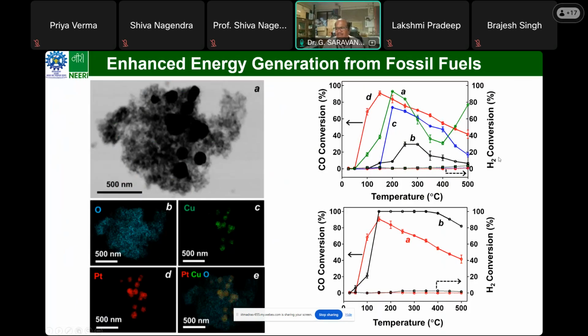There is no hydrogen consumption in this catalyst that we have prepared in our laboratory. Generally, low temperature is always better for this, and the prepared catalyst shows selective CO oxidation in the given temperature window. We also increased the oxygen concentration at the inlet to see whether there is any difference in CO conversion efficiency. Interestingly, even with 6% oxygen in the inlet, hydrogen conversion is not happening up to 200 to 250 degrees centigrade.